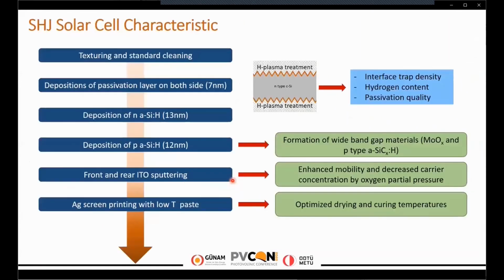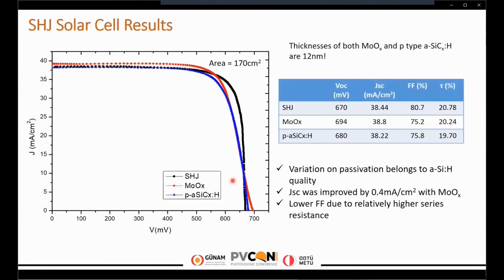This brings me to solar cell results. Here you can see the JV graph of the three different structures. The black one represents the standard silicon heterojunction solar cell. On the red one, we have molybdenum oxide on the front side of the solar cell, and on the blue one, we have P-type amorphous silicon carbide. The thicknesses of both emitter layers are 12 nanometer. On the table, you can see the solar cell parameters.